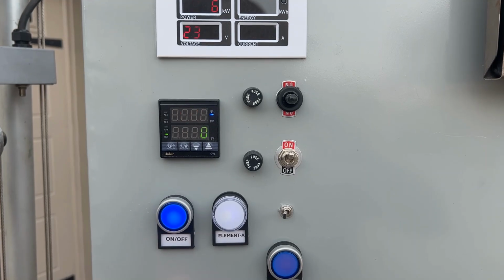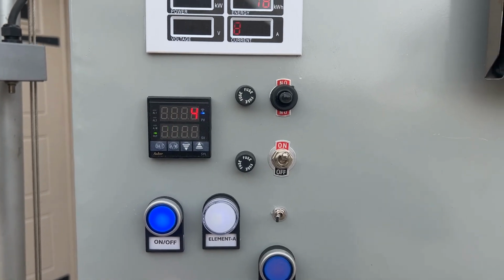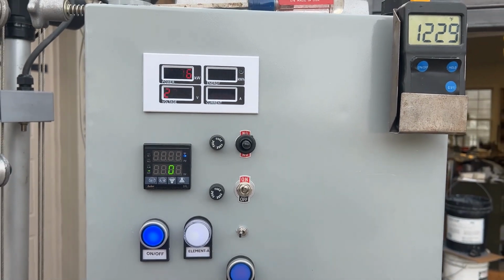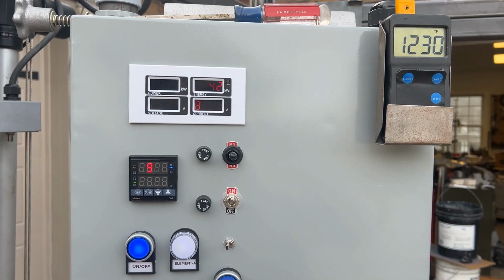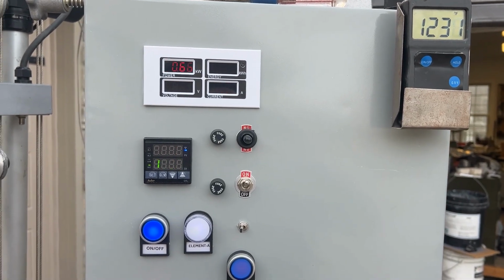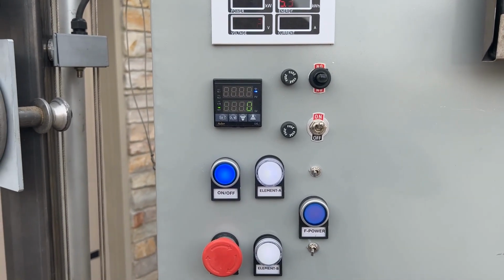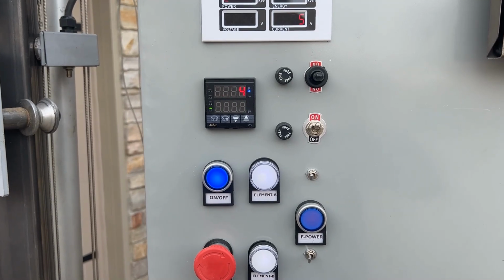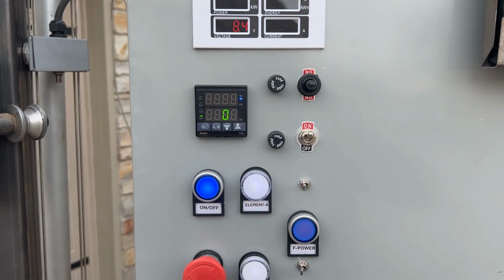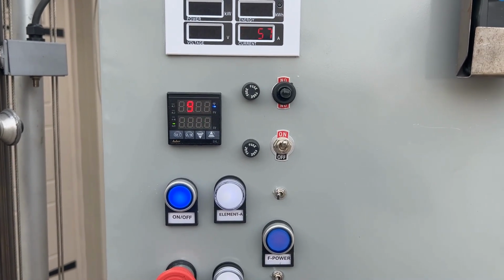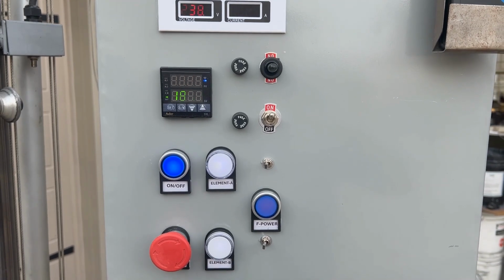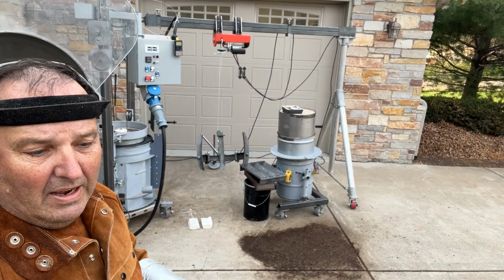So after about 10 minutes here, that annular gap between the crucible and the wall is at 1200 degrees plus, and the center of the lid above the crucible is at about 960 degrees. So the temperature's rising pretty fast. We'll have to see how long it takes to get to melt. Stay tuned.